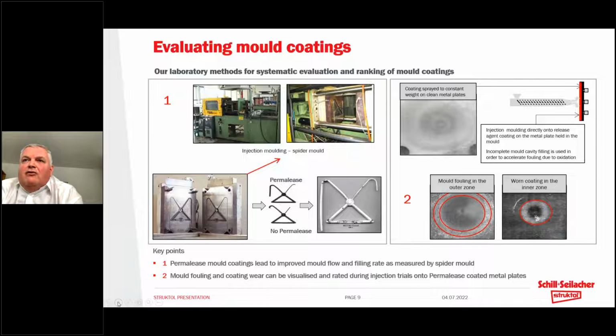So we can then measure the degree of wear of the mold coating, and you can see that in the bottom right image. It's not really black, it's just the difference in the reflection that we see when we photograph that, and we can see the mold coating starts to fail in the central region where it's subjected to very high shear and impact from the incoming compound. Later on, after multiple injection cycles, again, we can see on the outer edges of the molding a degree of mold fouling and mold deposits. So that really gives us also a very good indication not only of the flow property with method 1, but also the durability, wear resistance, and ability of the coating to directly resist mold fouling. Next, please.